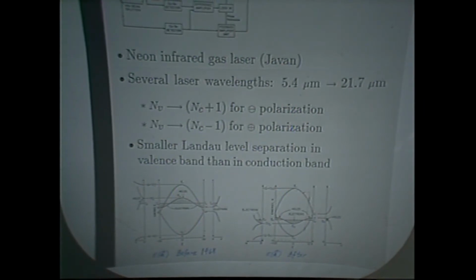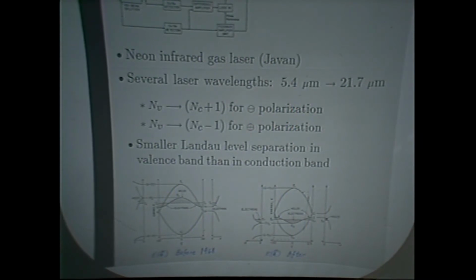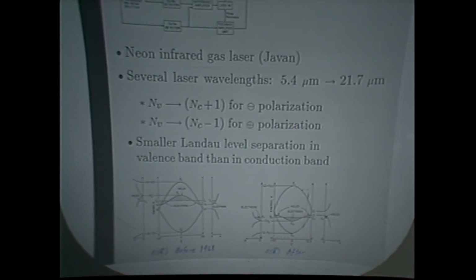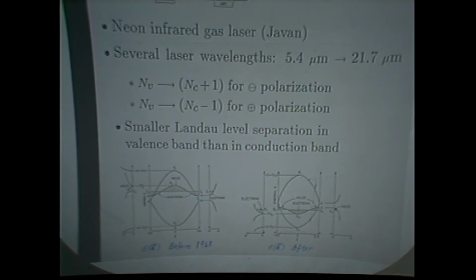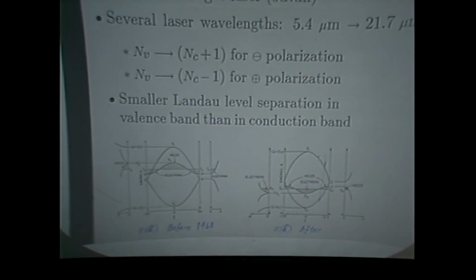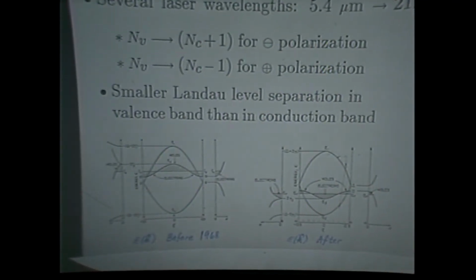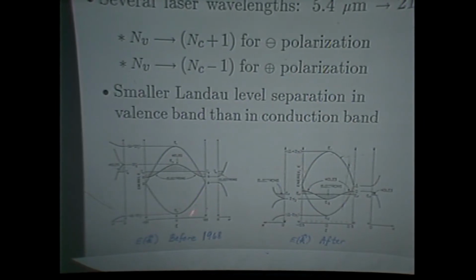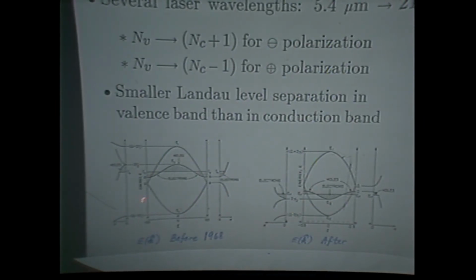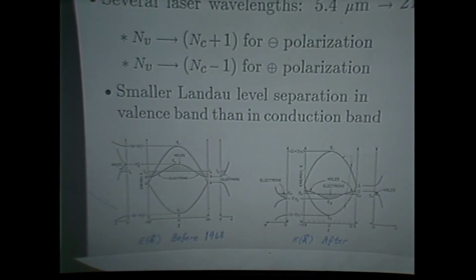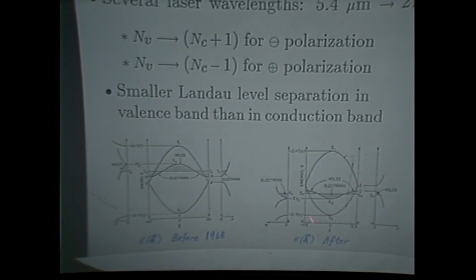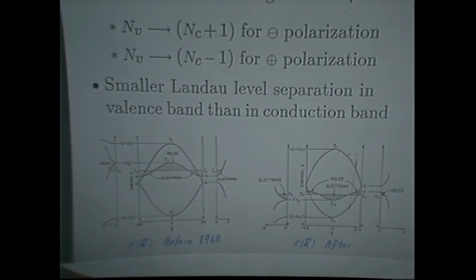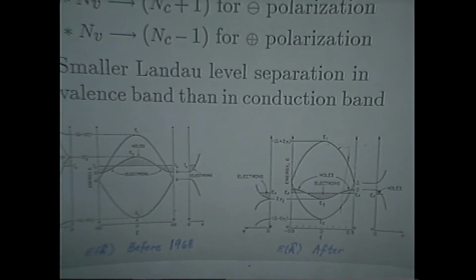conclusively that the Landau level spacing, that the magnetic energy level spacing in the valence band was less than that in the conduction band. Now, that doesn't sound very interesting, but the implications of that is that the band structure that everybody had been using for eons up till that point could certainly not be right and had to be turned upside down to get this one. This is the one everybody today knows, but we had to make that transition.